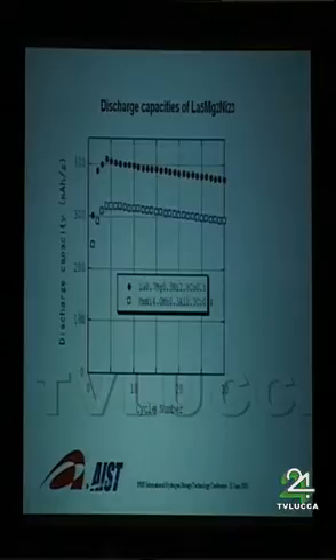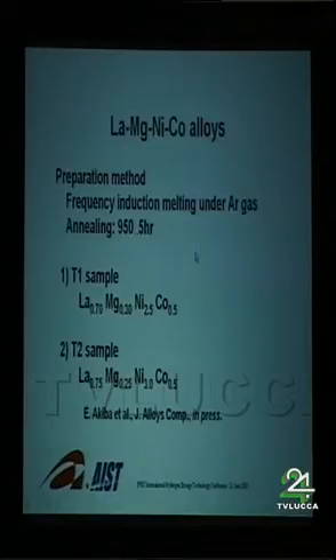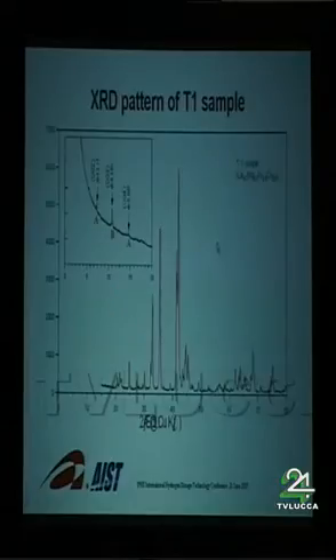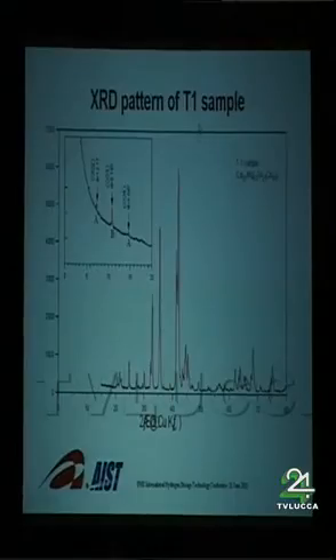So this is the discharge capacity of one superlattice alloy. This is a superlattice alloy, and this is a conventional AB5 type alloy. The capacity is about 20% larger than conventional alloys. And we prepared two different chemical compositions of superlattice alloys using the frequency induction melting method and argon gas. And this is an XRD pattern of one of the samples.